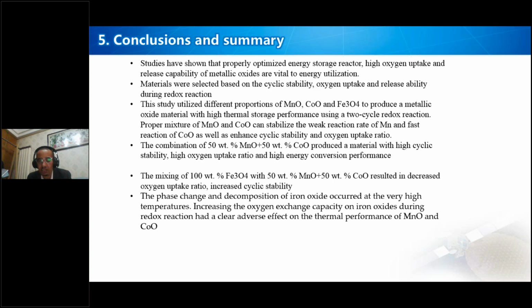We observe, from the theory and from other research work, that manganese is very weak for the reaction, whereas cobalt is fast for reaction. So the proportion balances the system, very weak to get normal, very fast to reduce. So the 50-50 proportion is still very important in this work. The combination of 50% by weight of cobalt oxide and manganese oxide produces a material with high cyclic stability, high oxygen uptake ratio, and high energy conversion performance.